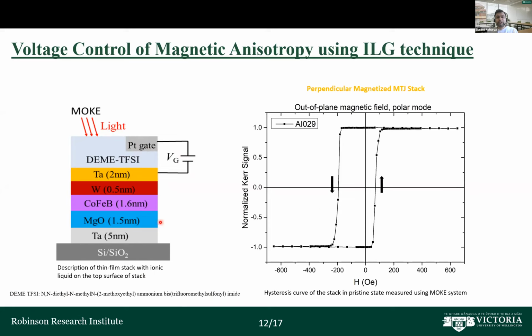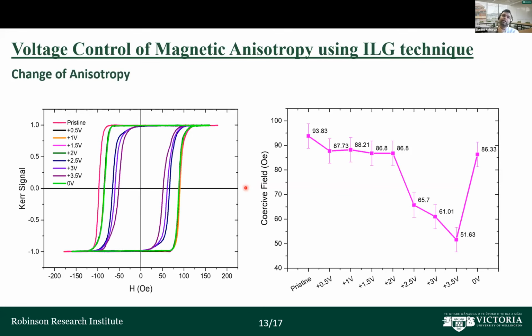In the pristine state of this thin film stack, you can see that the anisotropy is in the out-of-plane direction. If you look at this polar MOKE, it clearly shows the anisotropy is in the out-of-plane direction. Then what we did is we applied a voltage at an interval of 0.5 volt, and we waited for 5 minutes, and we saw that gradually the coercive field is decreasing. If you look at the right side image, when we apply a voltage of plus 3.5 volt, the coercive field decreased almost 50%, from 93 oersted to almost 51 oersted.